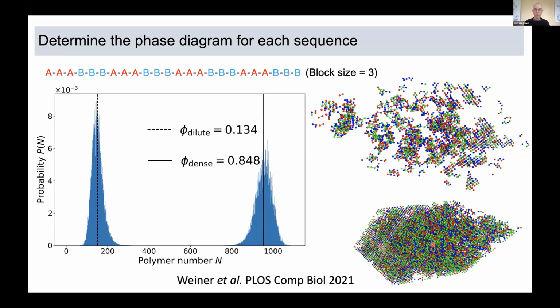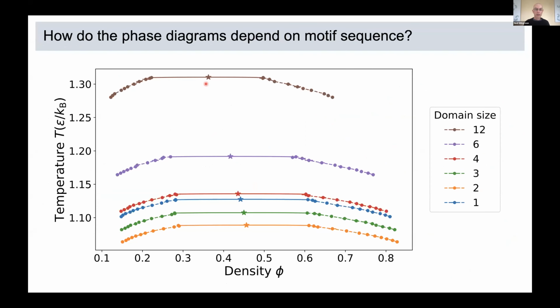And then we're going to see that. So here it is. But now for different lengths of these blocks. And so, okay, how do the blocks matter? And you could say, well, this has got a suppressed zero here. These are the tops of the phase diagrams, which we get very accurately this way. And you might say, well, I don't know, that's not so impressive. This went all the way from a critical temperature in the relevant units of 1.05 to maybe 1.3, not even a factor of 2. On the other hand, we're talking about biomolecular condensates in living systems. So if this guy is at room temperature at 300 Kelvin, this one phase separates 60 degrees Celsius lower. And so from a biological point of view, this difference is fairly huge.